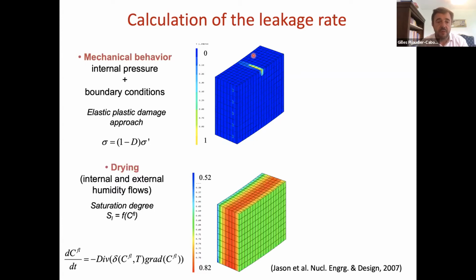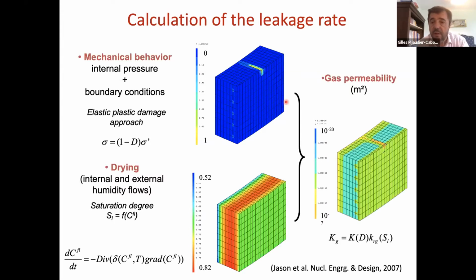Then you take into account the drying effect, and perform a calculation of the profile of humidity that is there. You plug this in, and separately perform a calculation of the leakage rate based on gas permeability. So you convert the information from the mechanical model and the hygrothermal model into a relative permeability to gas, and that provides a calculation of the leakage rate.